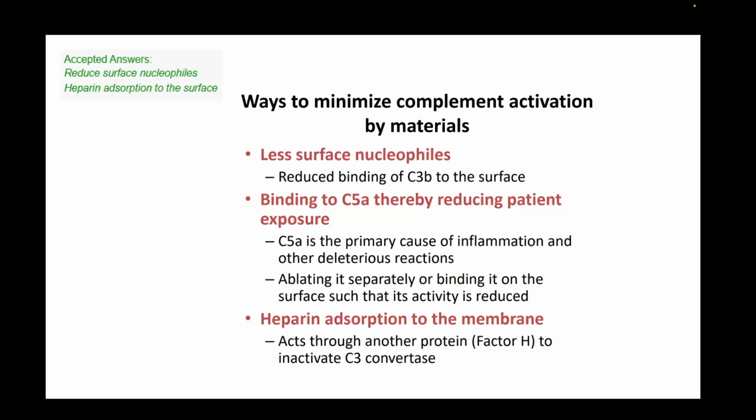From the question, the next option that was correct was heparin adsorption to the surface. Heparin coatings are a well-established method to reduce both complement and coagulation activation on biomaterials by inhibiting cascade components, and it acts through another protein, factor H, to inactivate C3 convertase.